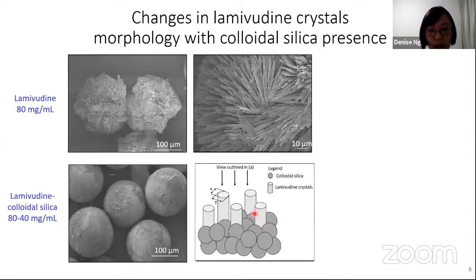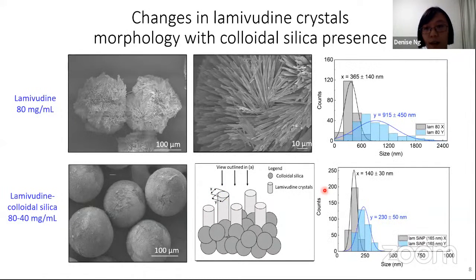Next, to quantify the changes in the morphology, we took top-down FESEM images, where we characterize the cross-sectional dimensions of the lamivudine crystals in the X as well as the Y dimension. And we observed that in the absence of colloidal silica, the distribution of the crystals in the X and the Y dimension are significantly larger and wider in distribution.